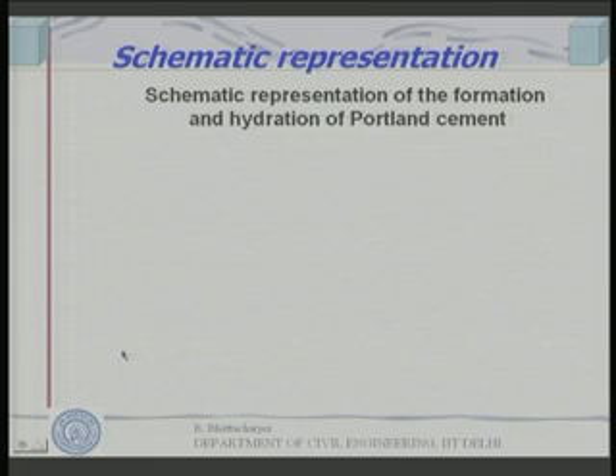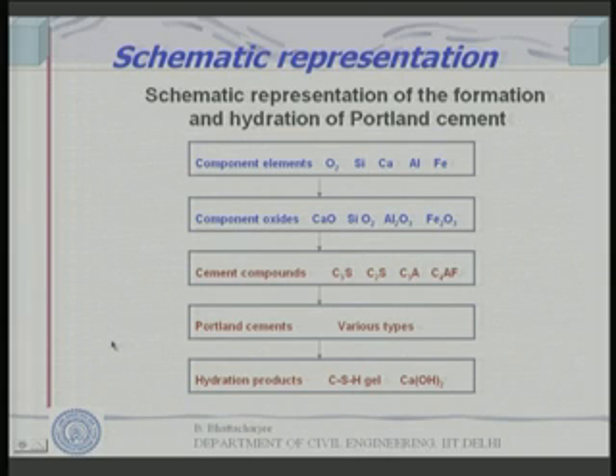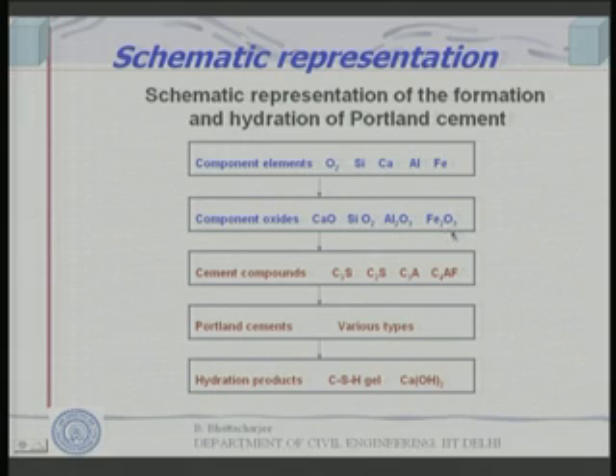If we do a schematic representation now of the formation and hydration of Portland cement, this is what we should see. First, element-wise, we have oxygen, silicon, calcium, aluminum and iron. So, we have these component elements, and these combine to form component oxides like calcium oxide, silicon oxide, aluminum oxide and iron oxide. This is ferric oxide, and then this combines to form the compounds C3S, C2S, C3A and C4AF. And when you add water, this forms what is known as CSH gel and lime, calcium hydroxide, slaked lime. We shall see this in a little more detail.